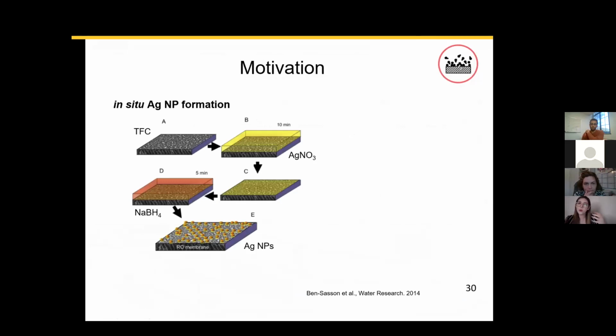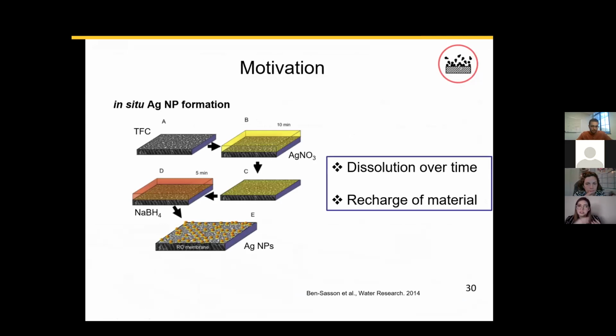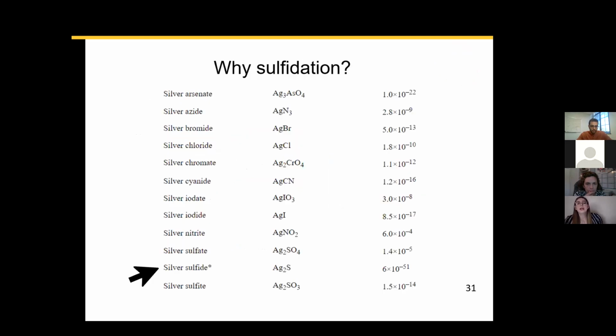This project was motivated because we know that in water treatment, silver nanoparticles are widely used for their antimicrobial or antibacterial properties. We tend to functionalize these membranes with silver nanoparticles to reduce biofilm formation. However, one of the main drawbacks is that we tend to have dissolution of the silver nanoparticles over time, and therefore we might have to recharge the material as we operate the system. And so we chose to use sulfidation. Why sulfidation? If we look again at the type of silver species that we can create, we saw that if we have sulfur present in water, we create really strong silver sulfide composites. And we know that sulfur has a really high affinity to silver.